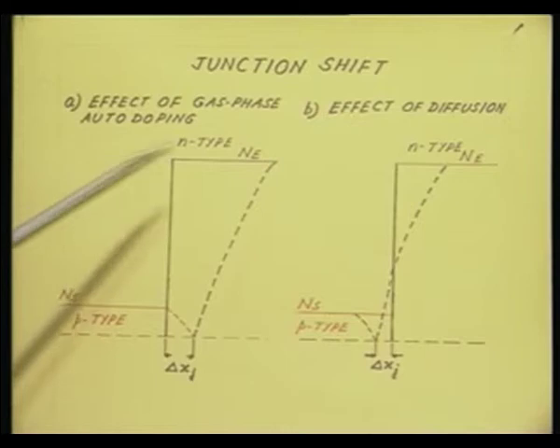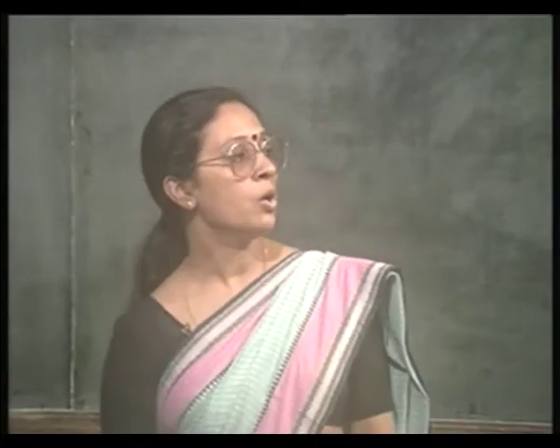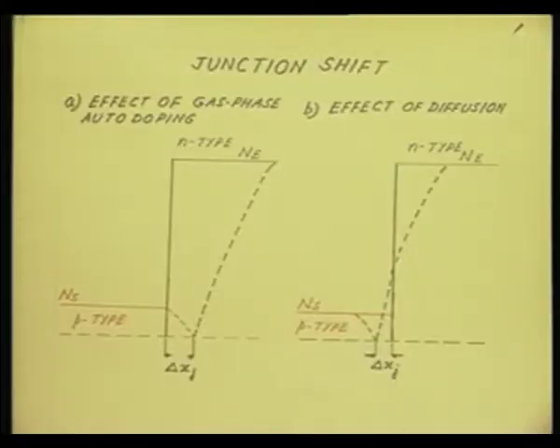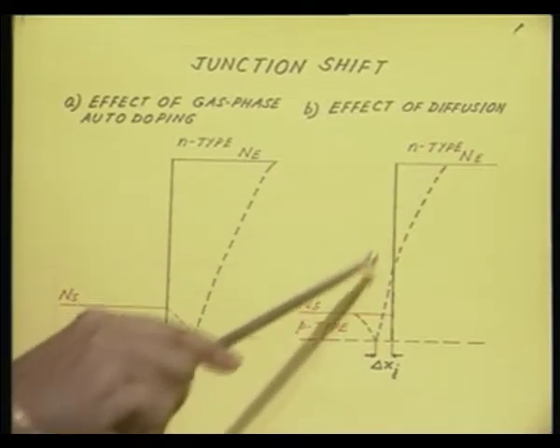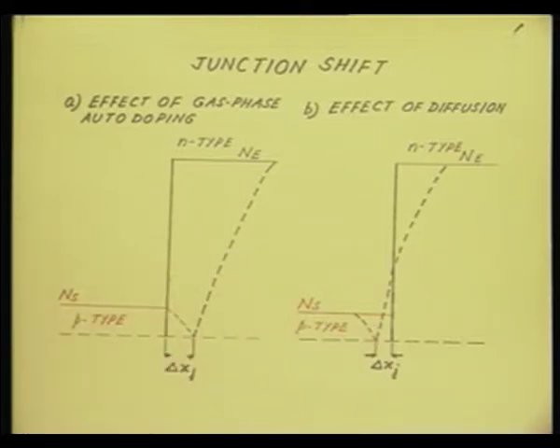Now, look at figure B. This is the effect of solid state diffusion. So, the diffusion means there will be movement of dopant from higher concentration side to the lower concentration side. Okay. Now, p-type dopants are present with a higher concentration in the substrate region. So, it will try to move into the epitaxial region, and n-type dopant is present at a higher concentration in the epitaxial region. Therefore, it will try to move inside the substrate. There will be intermixing, and in this particular case, since I have shown that the n-type doping concentration is very high, you can see that the junction has actually moved inside the substrate region, because there is intermixing.